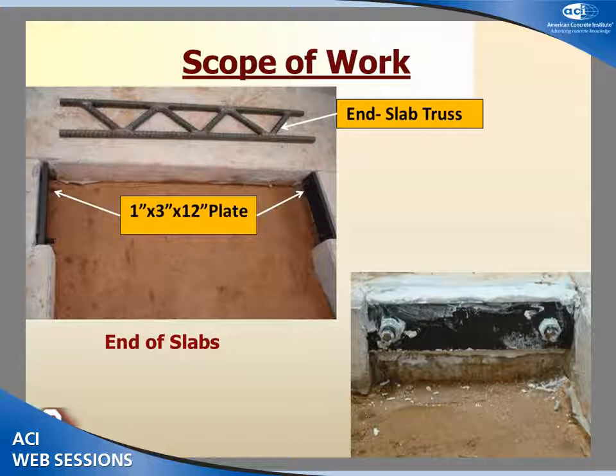From now on, I'm going to take you through the method of our research, to simulate the restrained shrinkage of the slabs on ground. We used steel trusses at the ends. So we made steel trusses and we welded these steel trusses to the plates. These plates were bolted and grouted to the existing slabs.